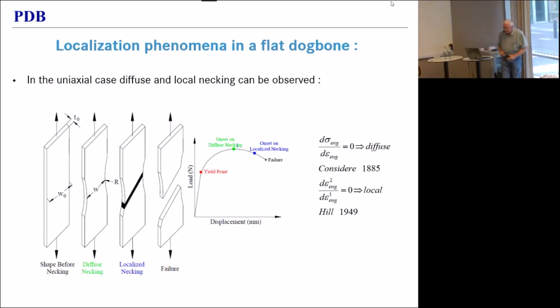Let's focus on necking a little bit. What is going on in a piece of steel that we subject to a tensile test? Well, you can actually distinguish four phases. Initially, you have homogeneous deformation. Then you have what we call diffuse necking, which is essentially a reduction in width of the sample. And then you have localized necking, which is what metal forming people are interested in. So you get extreme thinning in a narrow, skewed band through the sample, and that will then ultimately lead to